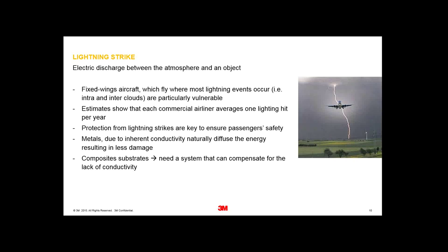That's never been particularly a problem with metallic aircraft because the metal is very conductive — the aircraft is effectively a huge Faraday cage that dissipates the lightning energy around the whole airframe. However, this is an issue with composites, because carbon fibre is not very conductive, meaning lightning strike energy is focused into one area and can cause quite severe damage.